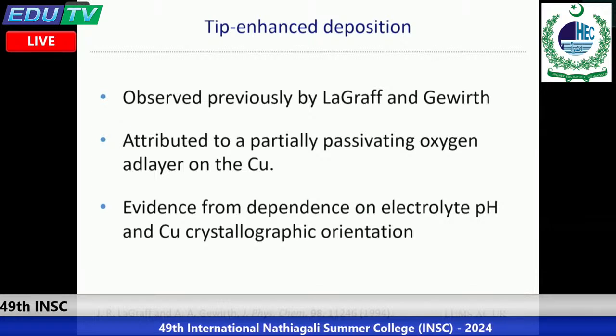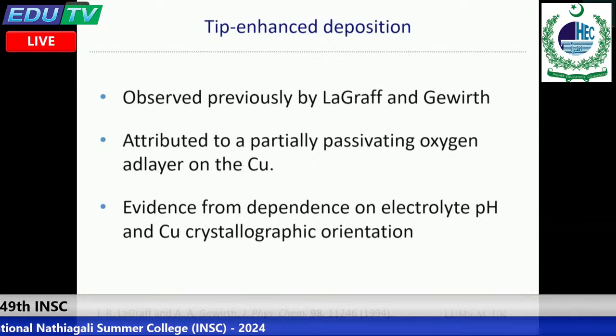And the adsorbate in this case is, according to how the pH was varied, something that tells you about the chemistry of the surface. From those experiments, it became fairly clear that what was being removed was an oxide species. So again, that goes back to what I said previously, that one of the ways that adsorbates affect growth is that they actually block surface sites. But another way that I also mentioned before is they can accelerate growth.